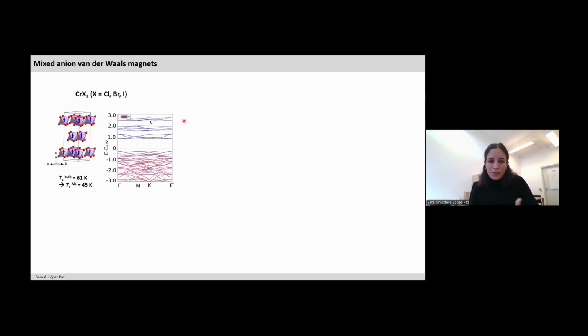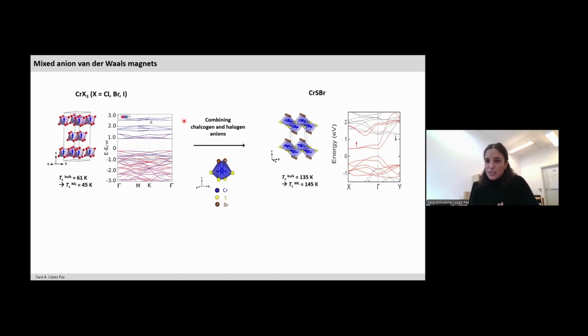So in order to try to tune the electronic properties of these materials, we identified that the combination of chalcogen and halogen anions can bring this mixture of properties. We see how now the chalcogen anions will give a more covalent character, and we have an anisotropic band structure where we have high conductivity along one direction while retaining the localization, which gives the magnetic order, in the other direction. So we definitely wanted to make this compound.